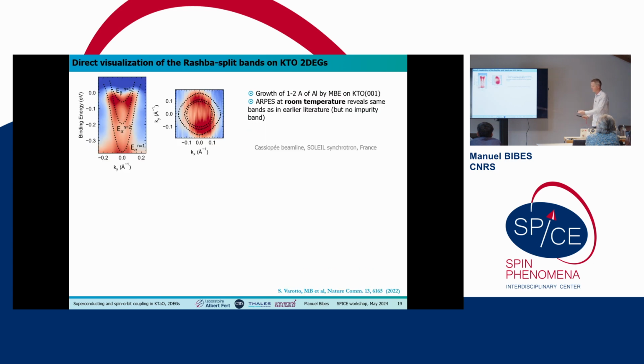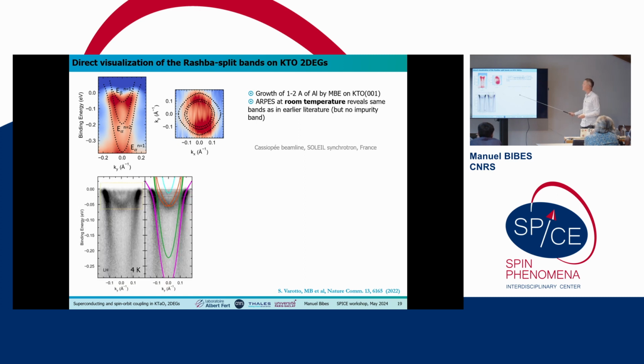So we tried to go back to measuring ARPES, with hopefully a higher energy resolution, a few years ago. And this is what we got at room temperature. You don't expect to have a very high energy resolution at room temperature. But in this case, the main features were consistent with that early paper. But at low temperature, we generated the 2DEG by depositing one angstrom of aluminum by MBE in situ. And we had much higher quality data. So this is the low effective mass band that we had identified.